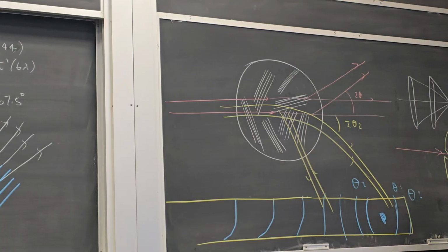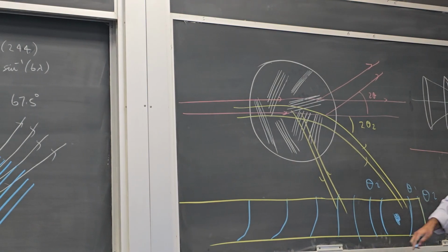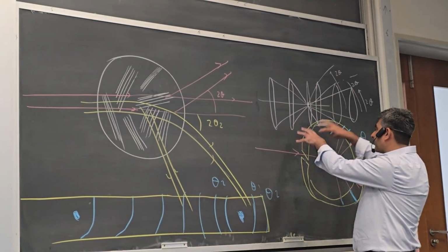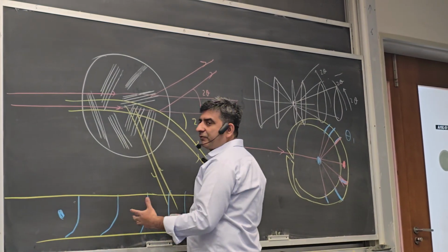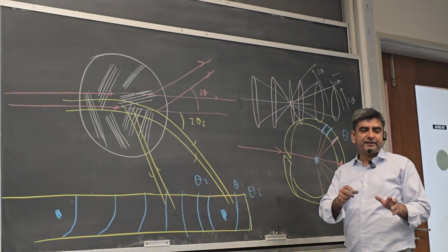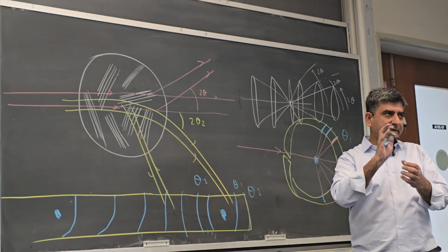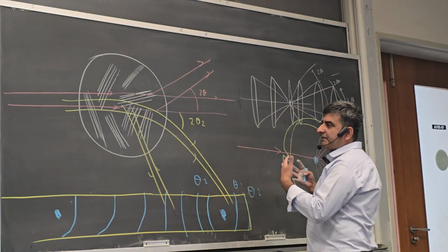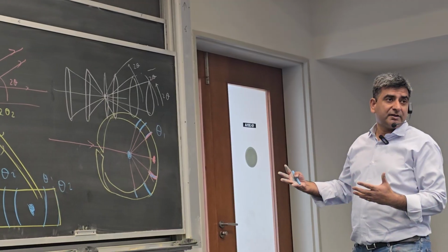I get all kinds of rings on the other side as well here. So these rings correspond to this side, which have 2 theta greater than 90 degrees, and some entrance pupil as well. So this is like a camera, and this is a photographic film. In the old times, before we had better detectors for X-rays, now they use scintillators, sodium iodide scintillators that give electronic pulses when X-rays impinge on them. But before that, one used these photographic films. But it's nice to demonstrate this because this actually shows the geometry of X-ray diffraction, how things are happening.